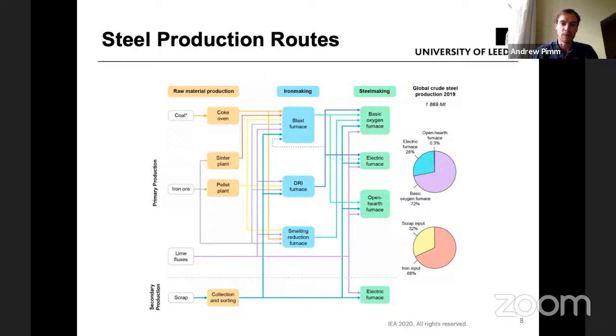So in terms of iron making, what's typically used to the highest level worldwide is the blast furnace. And I'll explain in more detail in further slides, but essentially you take iron ore, which is iron oxide, and you need to get that into pure iron. So you remove the oxygen by using carbon from coal. You convert coal into a concentrated form, which is coke, by heating it up in a coke oven, and then you mix the coke with the iron ore, your iron oxide, in a blast furnace, raise it to very high temperatures, and the carbon from the coke reacts with the oxygen, leaving you with pure iron.